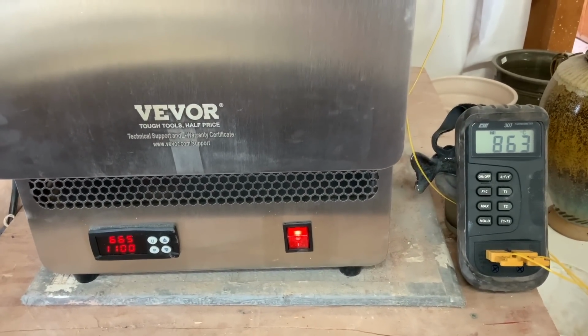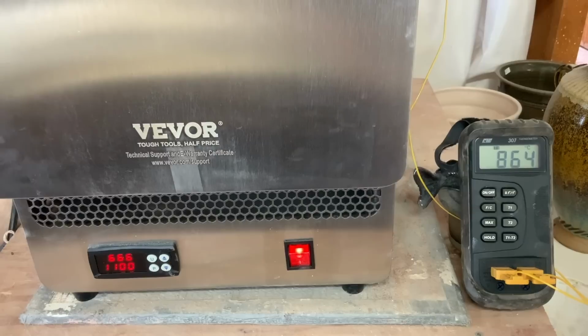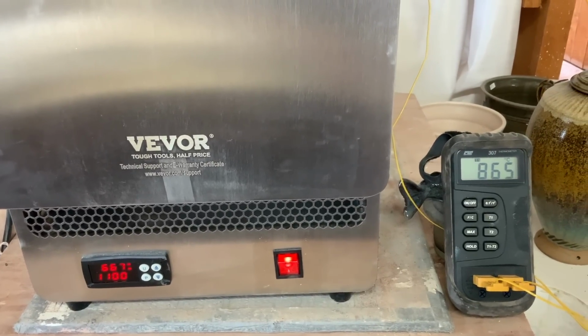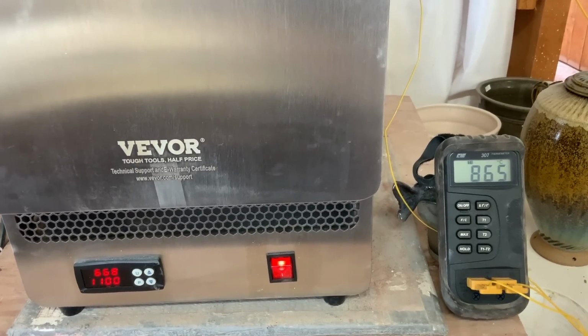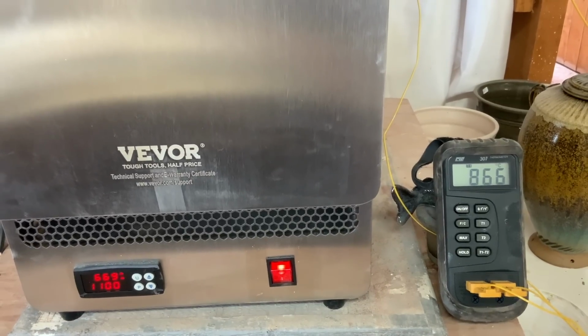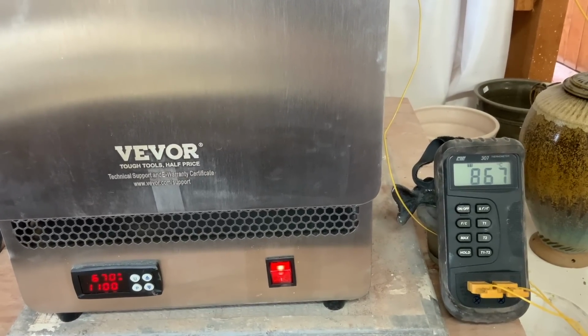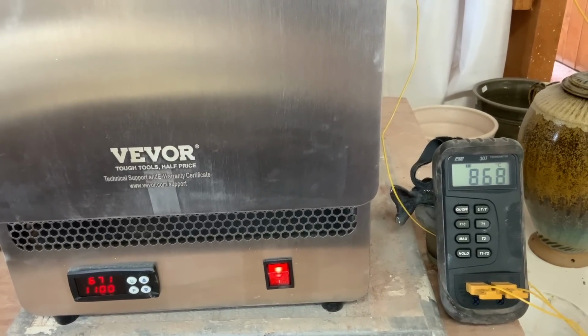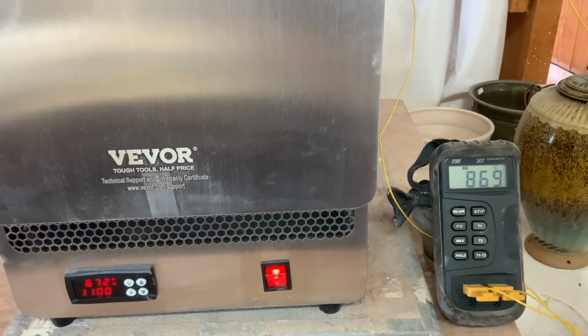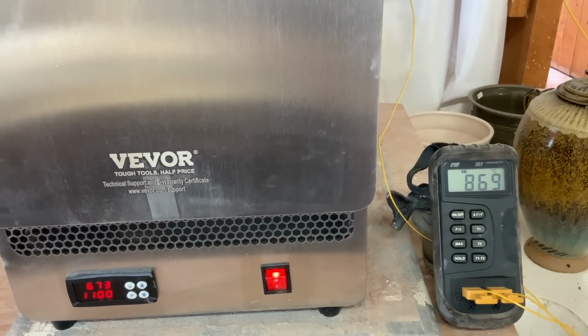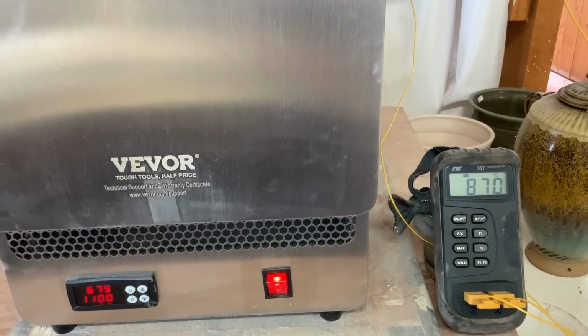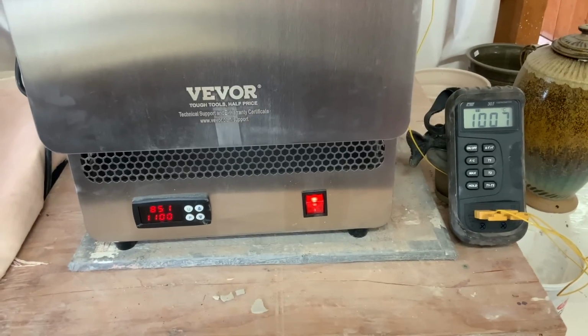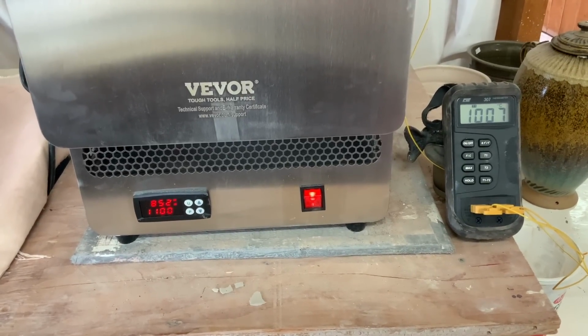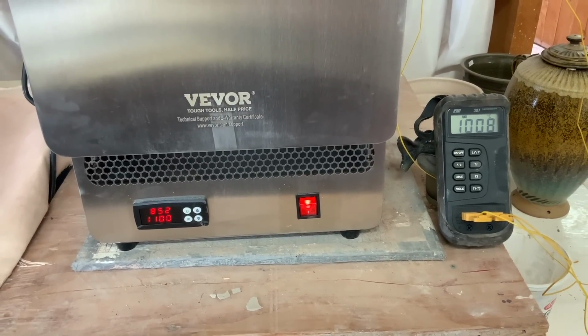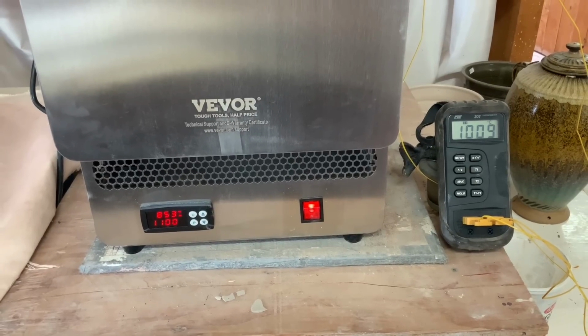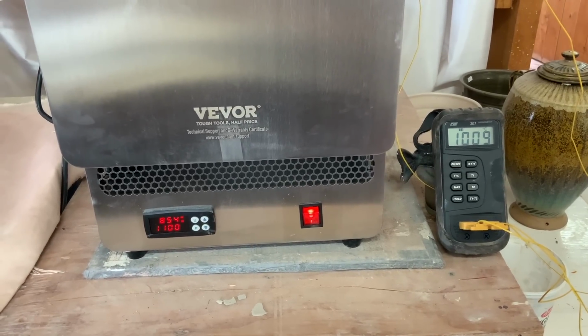Okay, we're about 20-25 minutes into the firing now, and you can see the difference on the temperature things. We've got 200 degrees difference in the pyrometer on the floor, which is supplied with the kiln, and my pyrometer hanging from the ceiling, and they're only 5 inches apart, so something is making their pyrometer read a cooler setting. Okay, now look, there's still 150 degrees difference in temperature, but there were 200 degrees. So the hotter it's getting, the more the temperature is evening out.